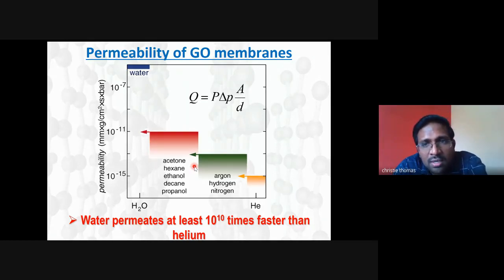Okay, so if you take a 2 micrometer thick graphene oxide membrane, all gases as well as organic solvents will be blocked, but the good thing is that water goes through. Okay, so it is highly permeable to water. Water permeates at least orders of magnitude faster than helium or other gases.